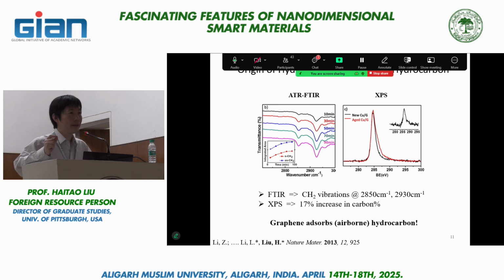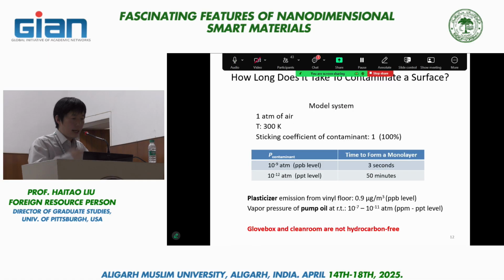Based on this assumption, you can calculate the amount of time needed to produce a monolayer coverage on the surface at different partial pressures of gas. You can estimate about 3 seconds is needed to form a monolayer if the gas molecule partial pressure is on the order of 10 to the minus 9. This is the so-called Langmuir time used by UHV scientists.